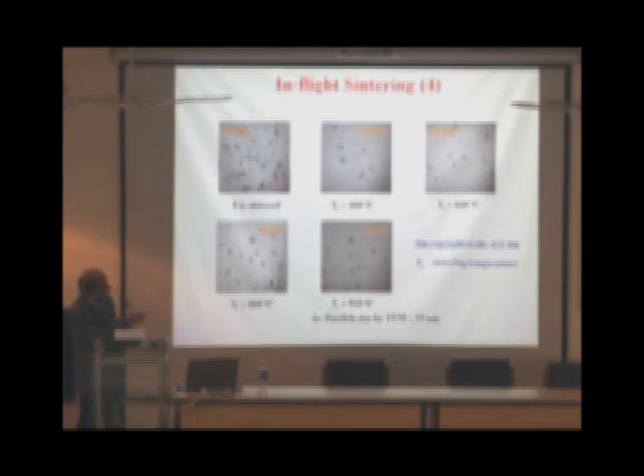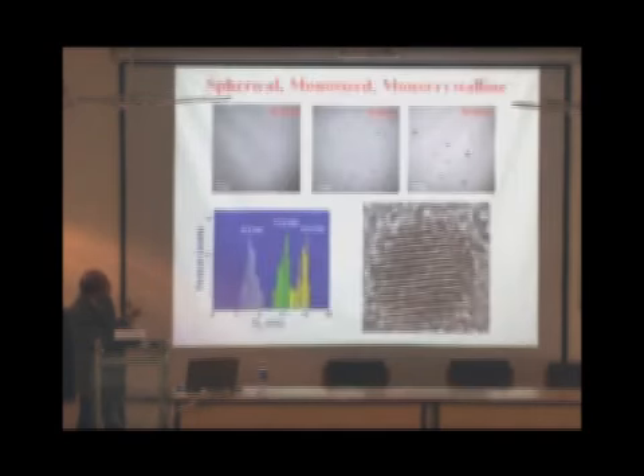spherical particle. Okay. And you can see that by giving different voltage to the differential mobility analyzer, you can select particles of different size. The size distribution is very symmetric, standard deviation is less than 1.05, and if you see one of these nanoparticles in the high resolution transmission electron microscope picture, it is almost monocrystalline.